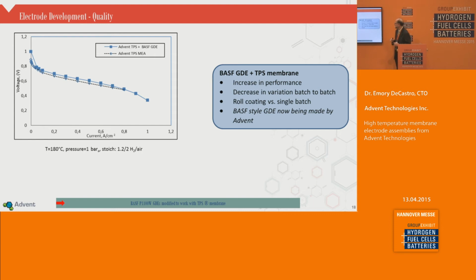And so what you see in this polarization curve is the black bottom dotted line. That's the standard Advent TPS membrane and the traditional electrode that was used for that platform. And now the upper curve is the blue boxes. This is now TPS membrane with the gas diffusion electrode that originally came from the P1100W. And there are actually several facts here. One, which is not shown, is that the variation from MEA to MEA decreased as we expected. Number two, the performance went up, which we always hope for. But more importantly, and also not shown in this plot, we decreased the precious metal loading by almost 1/2 using this P1100 style electrode. And so as it stands today, Advent is starting to make the gas diffusion electrodes using the BASF style.